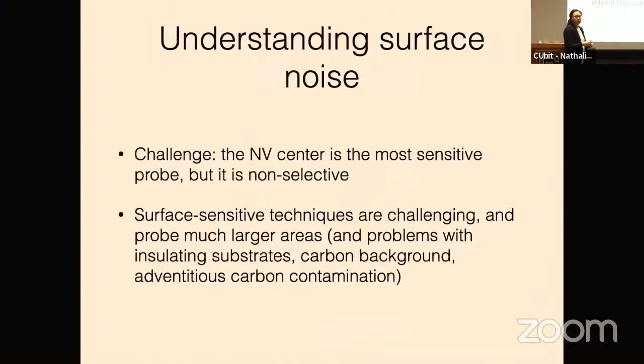Okay, so when I started my position at Princeton, we set out on this somewhat crazy project to try to understand this surface noise in detail. And the challenge here is that the NV center is a very sensitive probe, but it's really non-selective. If you measure the NV center, it just kind of tells you, my T2 is lousy. And you can take it one step further and ask, is your T2 lousy in this frequency regime or this frequency regime? But that's pretty much it. It doesn't tell you anything about the microscopic origin of what you're staring at.